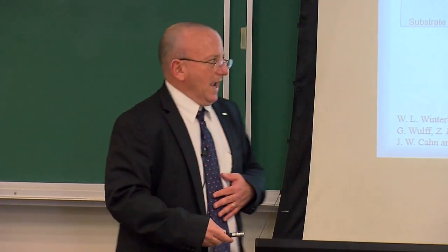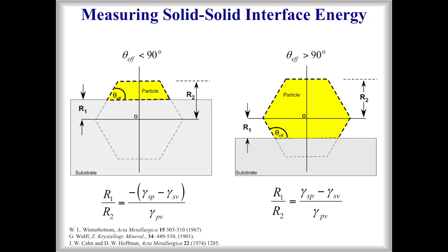That's it. At the end, for this example on the right, where this effective contact angle is quite large, we have this equation where the ratio between the distance from the center of the Wulff point to the interface, R1, and the distance to any of these facets, in this case I took R2, but it could be out here as well, reflects the relative surface and interface energies of the system. So we get a relative value. That's all we can get out of this, unless we know, let's say, the surface energy of the particle and that of the substrate, and then we can actually get at the absolute interface energy itself.